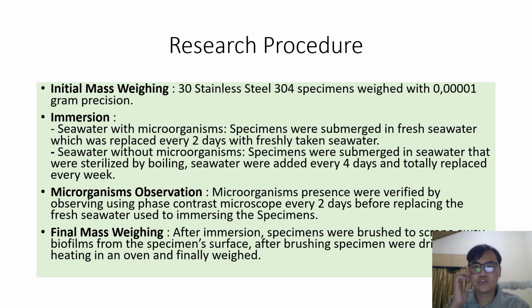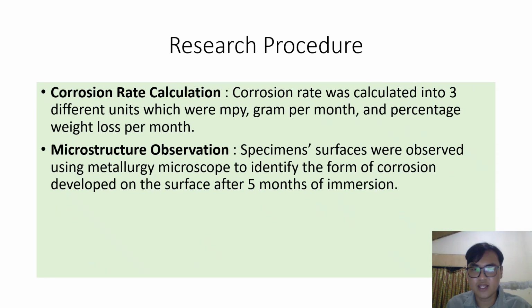We created two immersion environments: fresh seawater that was replaced every 2 or 3 days to maintain live microbial activity in the water, and sterilized seawater, which is boiled to eliminate the microbes in the water. After immersion, we cleaned the specimens and weighed them again to determine mass loss. We then calculated the corrosion rate in 3 different units: grams per month, percentage weight loss per month, and mils per year. Finally, we observed the surface microstructure using a metallurgical microscope.